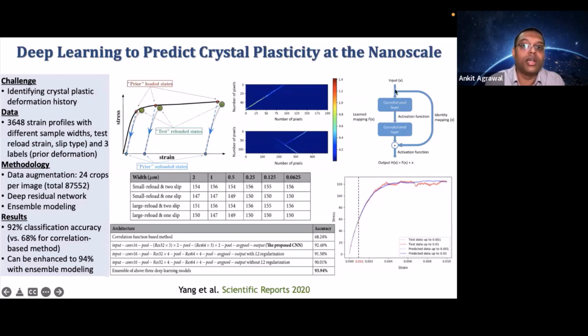But then we used this residual learning idea, and we found that the baseline model can give 68% accuracy, which is actually quite good, because for a 3-class problem, random guessing will only give you 33% accuracy. So the base model, the correlation-based model, was already 68% accurate. But when we applied our proposed model, we could get 92%, and if we combine the top performing models, it could reach almost 94%. And this was very fascinating to our collaborators.